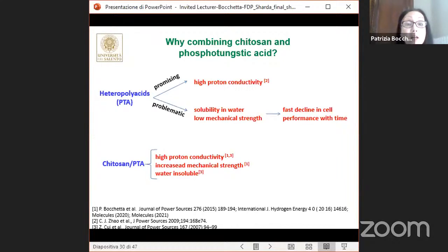However, it has a very low mechanical resistance and a high solubility in the water produced at the cathode of the fuel cell by oxygen reduction reaction. And this strongly limits the durability of the fuel cell power output. So to overcome this issue, in general, literature has tried to put phosphotungstic acid into a stable matrix.